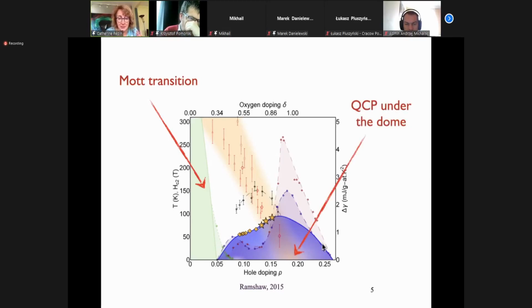So we could claim that there is a QCP, a quantum critical point, under the dome. Namely, the pseudogap would be a real phase transition, ending at zero temperature, producing a lot of fluctuations at this quantum critical point. We don't know the order parameter. It might be very complex, very unusual. But once we know what it is, we will solve the mystery of the pseudogap. So here you see an enhancement of the specific heat divided by temperature, which is proportional to the fluctuations. This is a kind of experimental incentive that we have indeed a quantum critical point under the superconducting dome.